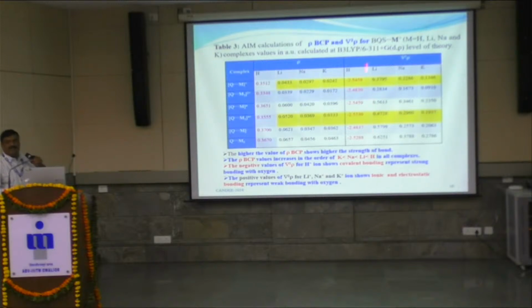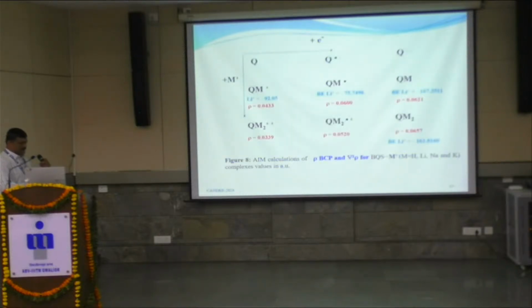After binding of hydrogen with the oxygen, these del square rho values are reported as negative, which shows covalent bonding. The positive del square rho values for lithium cation, sodium cation, and potassium cation represent either ionic or electrostatic bonding with oxygen. The same values are reported here for the various states of the quinones for lithium cation binding and rho BCP change. These values are for lithium only.